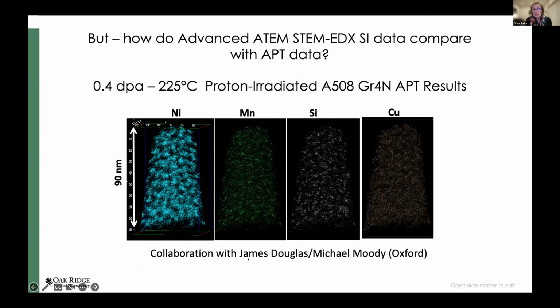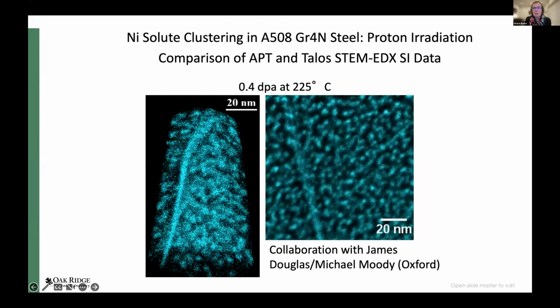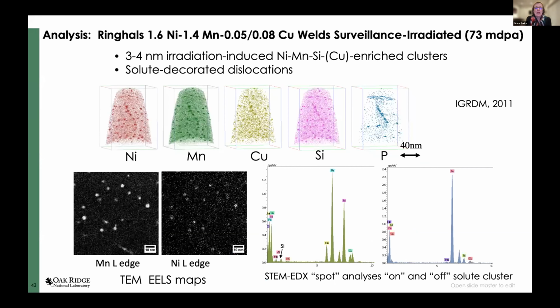So we're working with our colleagues at Oxford, including James Douglas and Michael Moody, and they did some beautiful analysis of this steel. And we can see our nickel and manganese, silicon, and a slight hint for copper. But let's compare them. So we've got the atom probe tomography reconstruction, and we've also got the elemental map for nickel from our STEM EDX data on the Talos. And actually, they're pretty amazing. This is incredible what we can do now compared to what was possible 20 years ago.